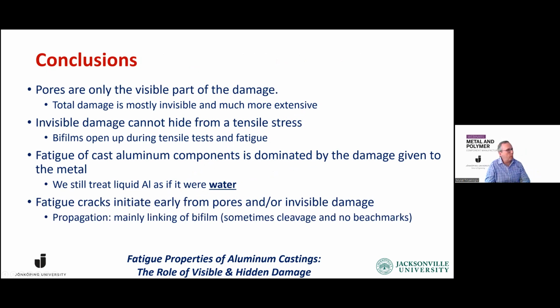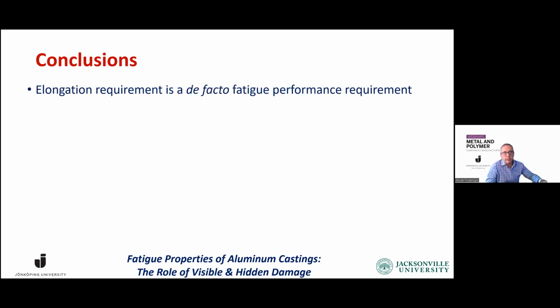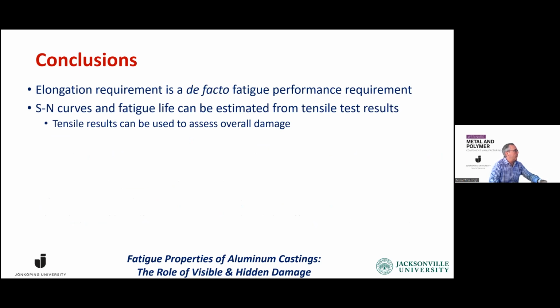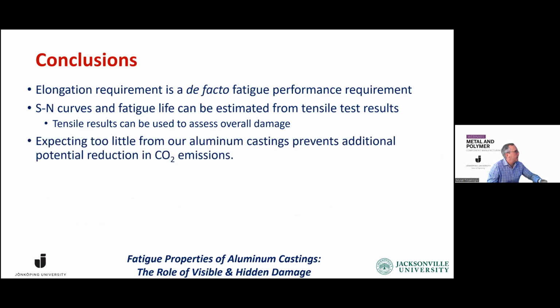Fatigue cracks initiate early from pores and/or invisible damage. Propagation is basically linking of bifilm, sometimes there is cleavage and no beach marks. We don't really see much of a fatigue stage during the fatigue of cast aluminum alloys. Elongation requirement is a de facto fatigue performance requirement. The SN curves and fatigue life can be estimated from tensile tests. And expecting too little from our aluminum castings, just because we treat them as if they were water, prevents additional potential reduction in carbon dioxide emissions.